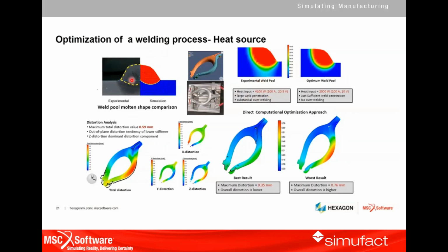Okay. So this is the experimental setup, and this one is the simulation, showing how we can get the close heat-affected zone, or the heat-affected fusion zone, in the simulation and in the experiment. They wanted to optimize the weld pool so that using less power, we should be able to get sufficient heat penetration, as well as the optimum parameters. In this study, we found that using half of the energy, first we were using 4,000 watt energy, after that, with 2,000 watt itself, they were able to get the optimum penetration without over-penetration. So this helped to reduce the distortion at the end of the simulation.